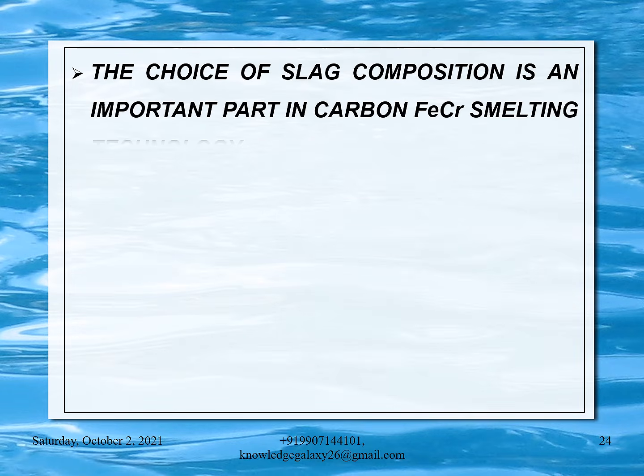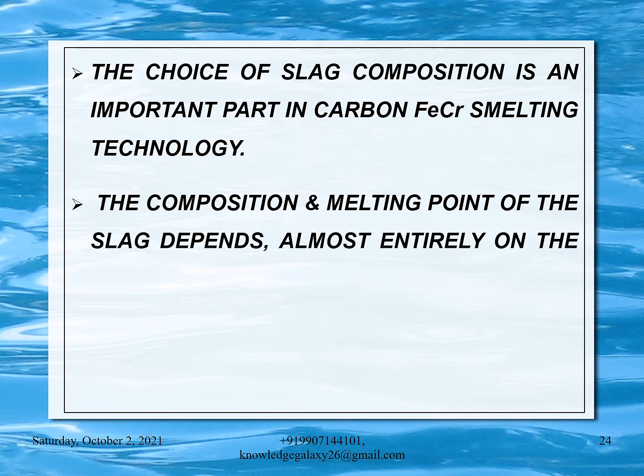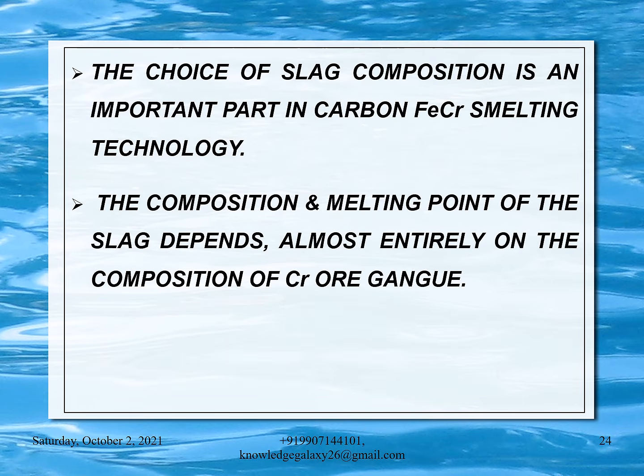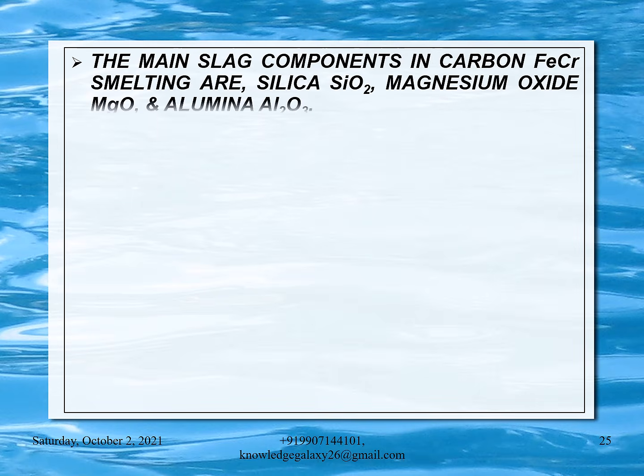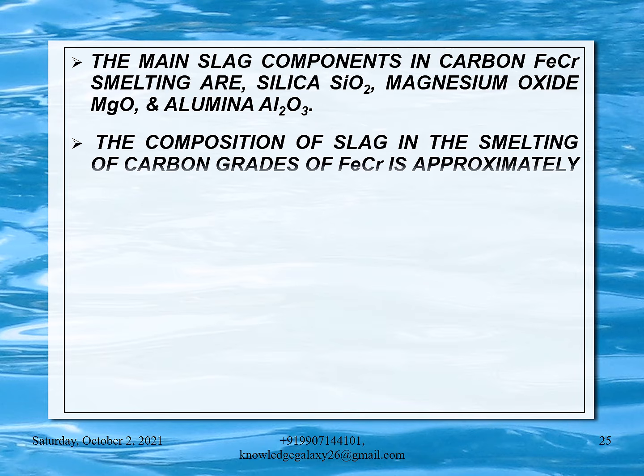The choice of slag composition is an important part in carbon ferrochrome smelting technology. The composition and melting point of the slag depends almost entirely on the composition of chrome ore gangue. The main slag components in carbon ferrochrome smelting are silica SiO2, magnesium oxide MgO and alumina Al2O3. The composition of slag in the smelting of carbon grades of ferrochrome is approximately as follows.